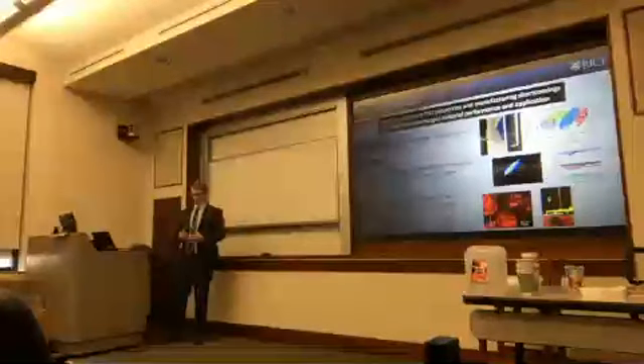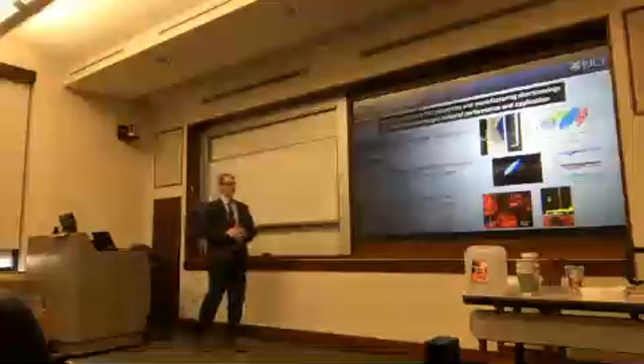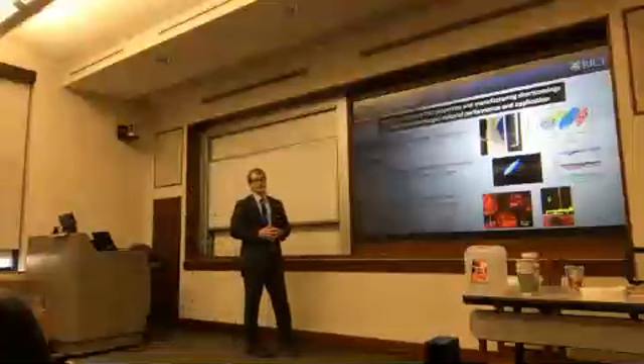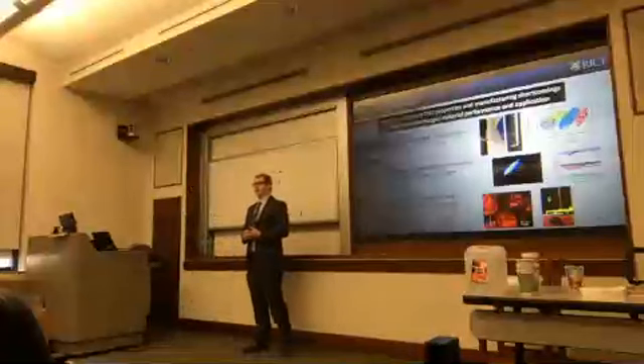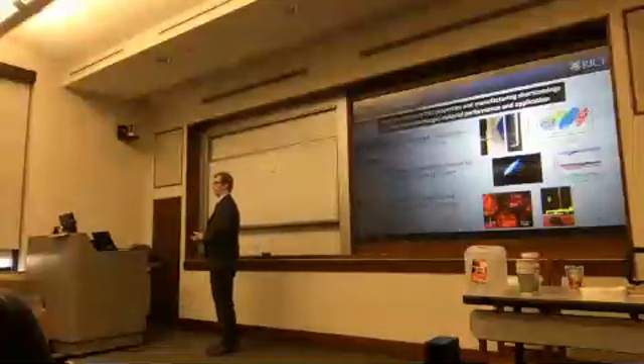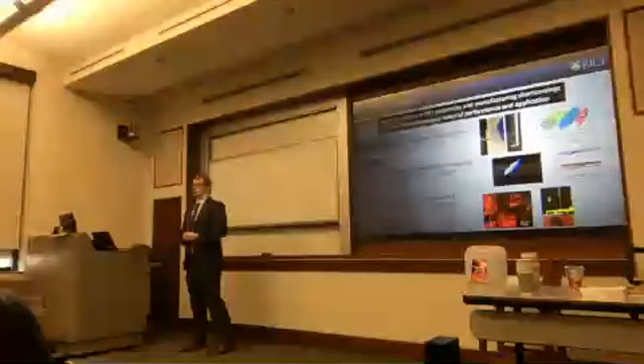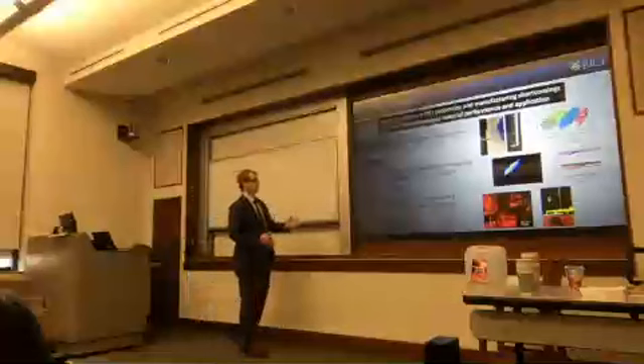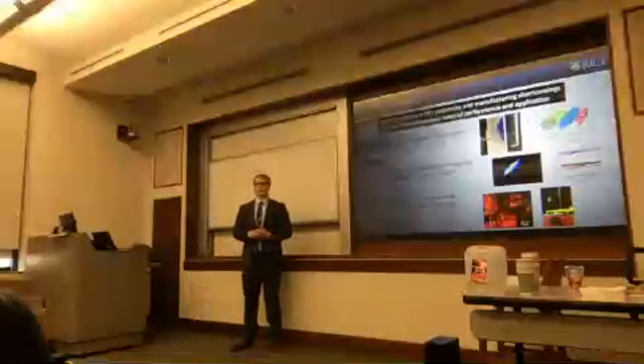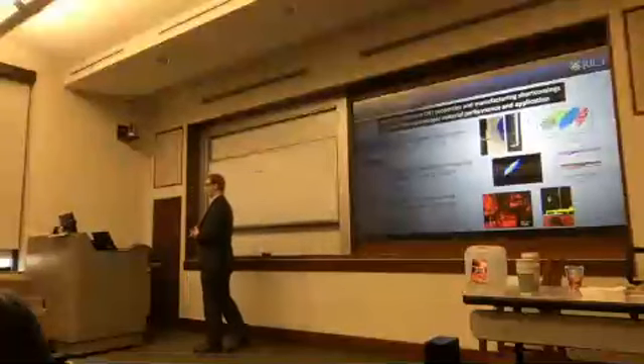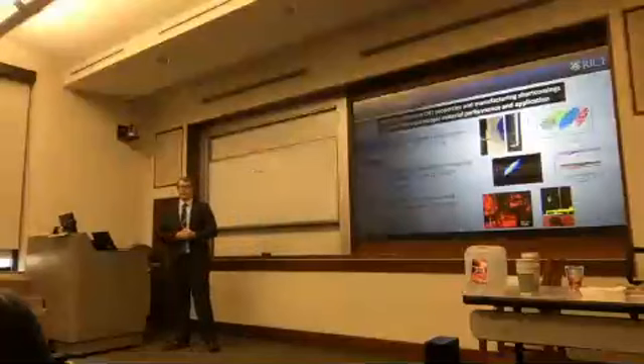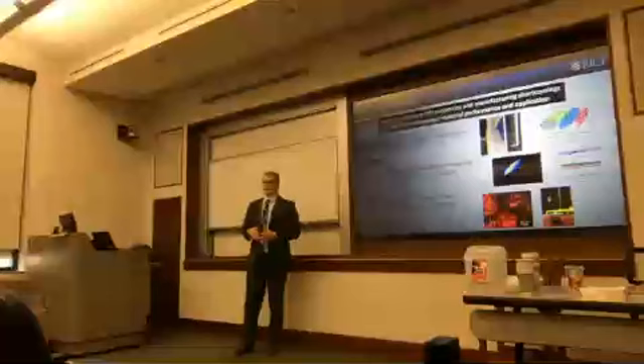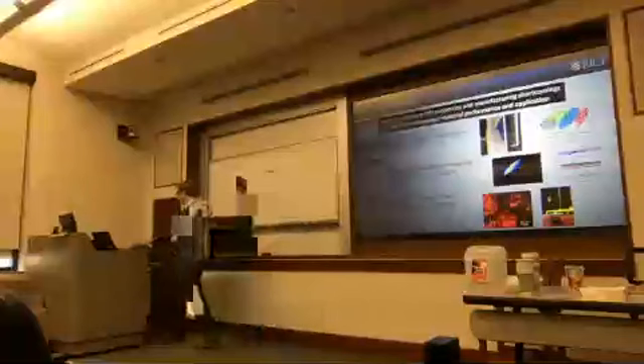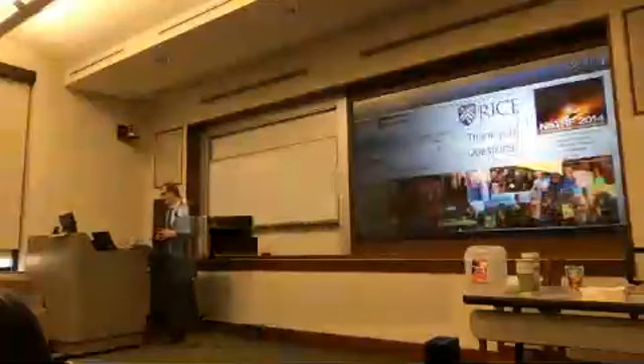So to conclude my talk, I'll just remind you that in the beginning we talked about how we can characterize structure-property relations in carbon nanotube fibers by producing aligned films and transforming those into high-performance nanotube fibers. We developed a microscopic technique for measuring linear density of short carbon nanotube fibers, and then we demonstrated [a new processing method] yielding high-performance macroscopic materials. So that is everything I have.